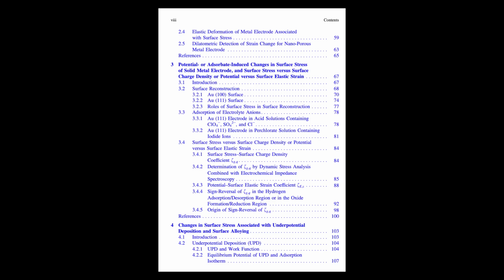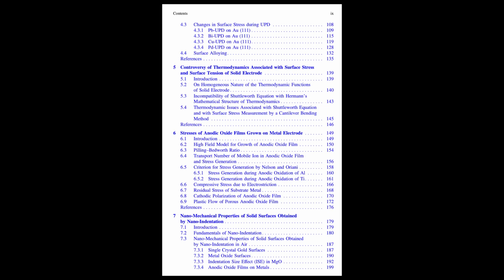That's good. It does, although interestingly, for some materials like nanoporous gold or maybe platinum electrodes, we sometimes see a reversal in the sign of these coefficients. A reversal? What does that mean? It suggests that the unique electronic structure of these very high surface area materials plays a really critical role in how they respond mechanically to electrical changes. So the actual physical shape of the surface, flat plane versus spongy network, can dramatically change how it behaves.